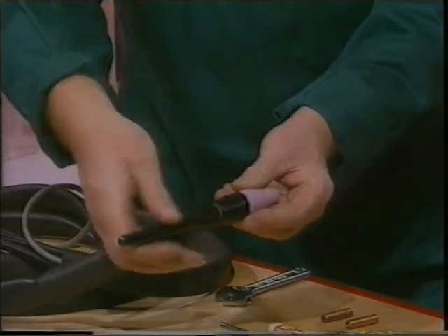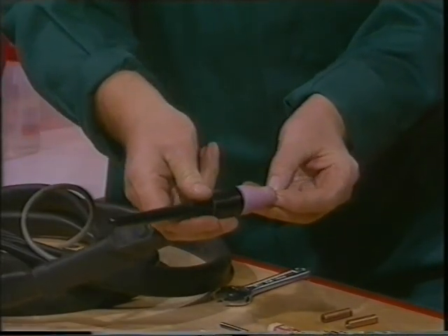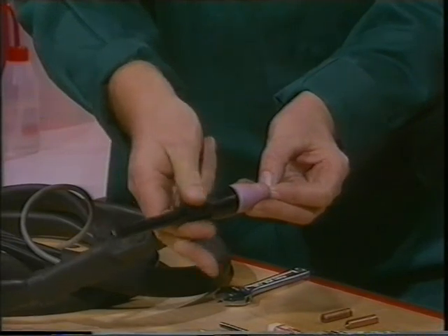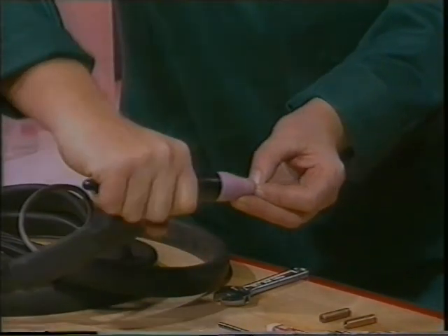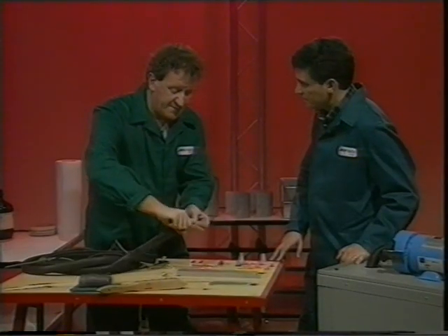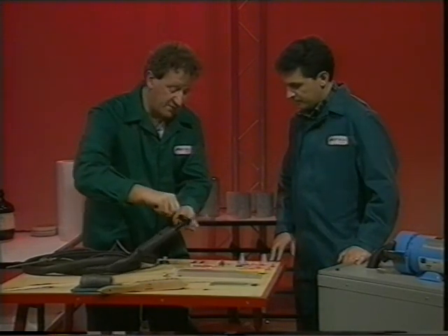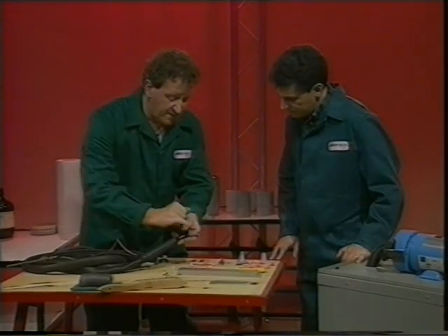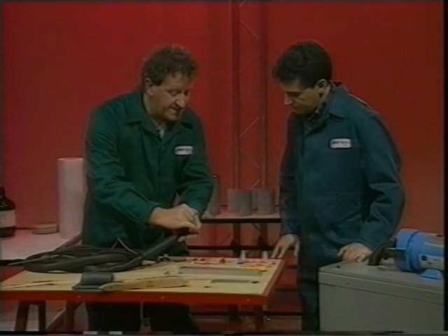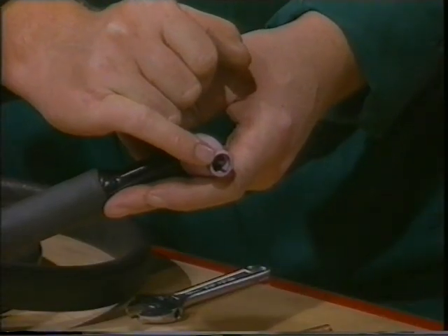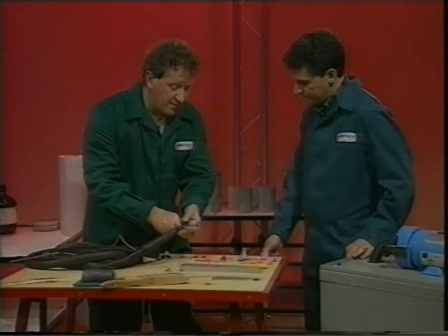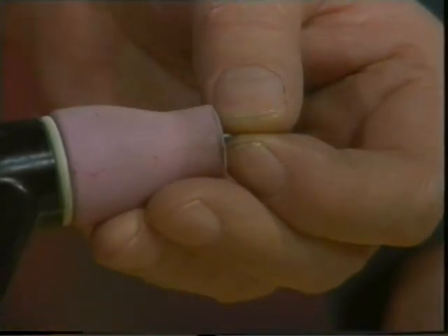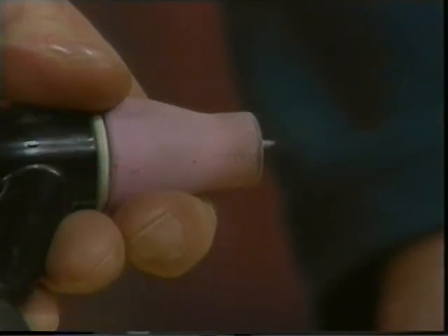When it's in place, we can determine now how much tungsten stick out we need from the end of the nozzle. How critical is that? It's critical to provide sufficient gas coverage for the weld. So a stick out of maybe 8mm would be suitable for fillet welding. If we wanted to weld a butt weld, we might need slightly better gas coverage, so we'd push the tungsten to maybe 6mm stick out.